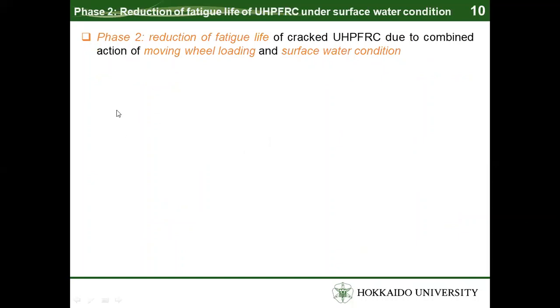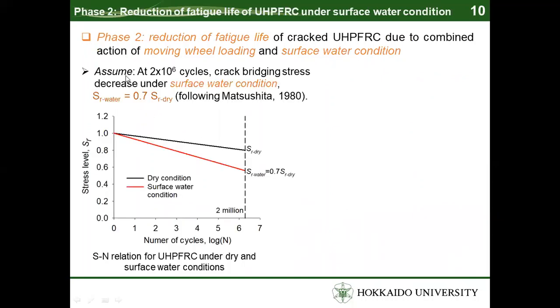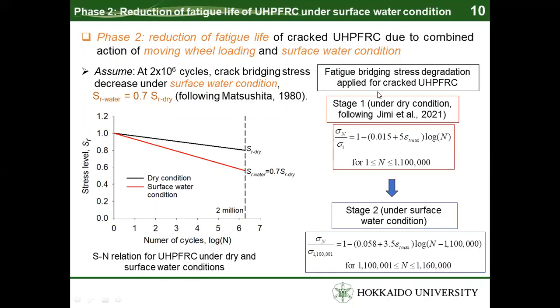For the second phase of material model, it is assumed that at 2 million cycles, crack bridging stress decreases under surface water conditions, and the stress level in water conditions is chosen as 70% of that from dry conditions. And the bridging stress degradation applied for cracked UHPFRC under surface water conditions in stage 2 can be calculated and shown in these equations.